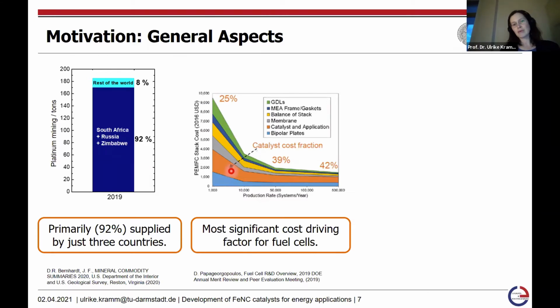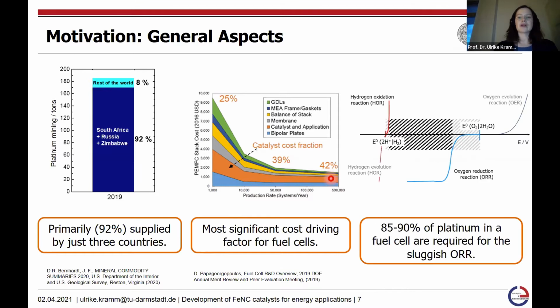Based on that, if we would like to reduce the costs of the overall fuel cell system, if we would like to go into this regime in terms of production rates, then of course we need to replace the platinum or really be able to lower it significantly in order to reduce further the costs of a fuel cell system. And when we have a closer look at the two electrochemical reactions, the hydrogen oxidation reaction and the oxygen reduction reaction, then we can see that the oxygen reduction reaction is quite inefficient.